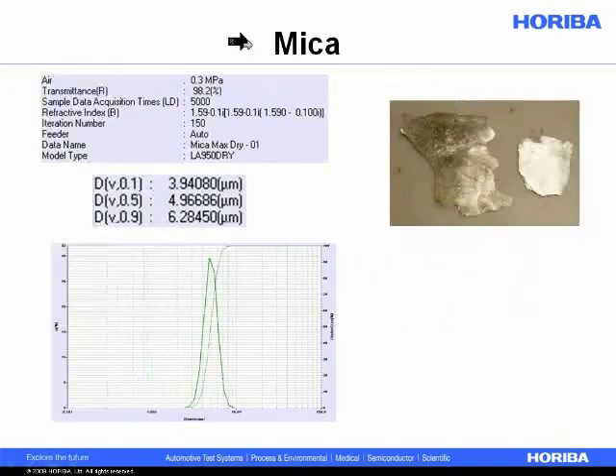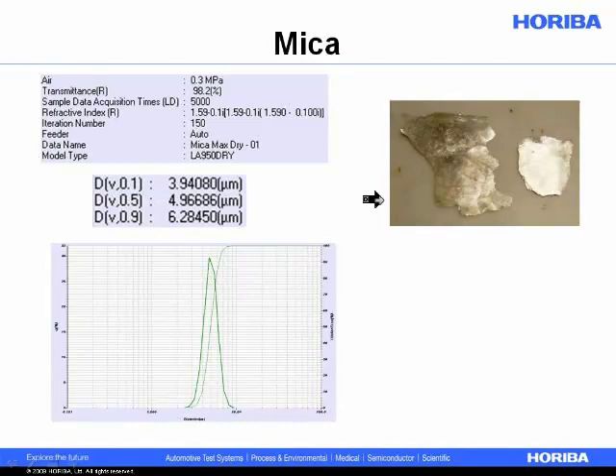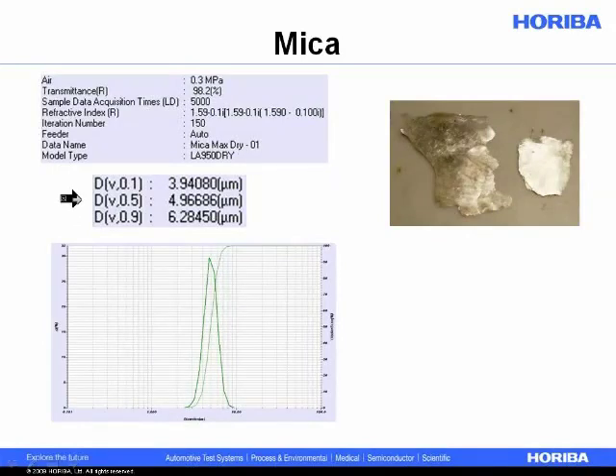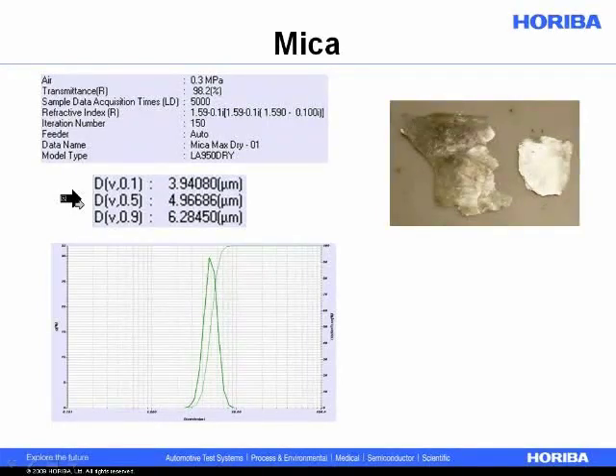We also bought some mica powder, which was not coated, to include in our handmade cosmetics. We see it's a fairly tight particle size distribution with a median of five microns. I would assume this mica was probably milled and then either sieved or separated somehow to create this nice narrow distribution of particles, which causes less segregation when mixing into other materials.